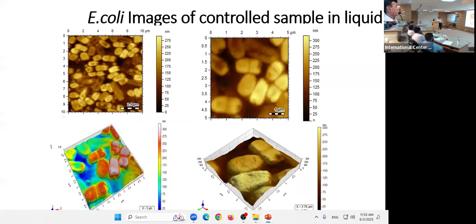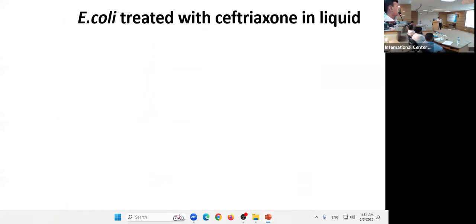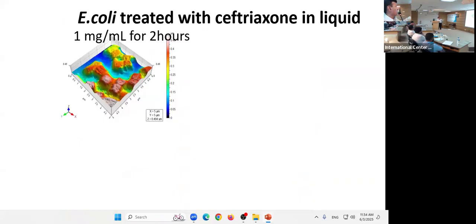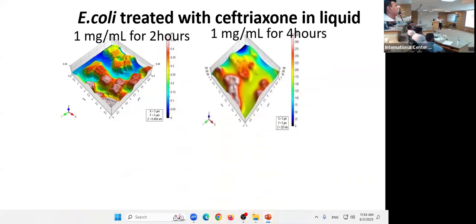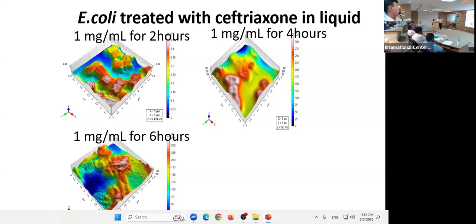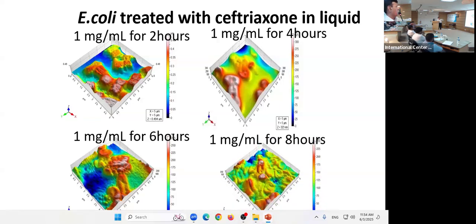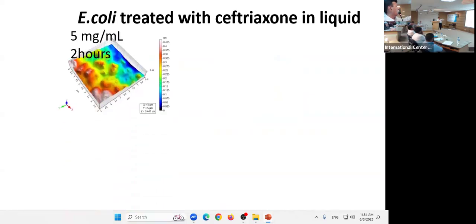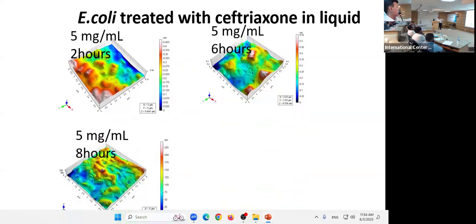Then these are the control samples of the E. coli, and then we treated them with ceftriaxone: 1 milligram for 4 hours, 1 milligram for 8 hours, and so on. This is 5 milligrams of ceftriaxone. You see that when we increase the concentration and time, the bacteria are disappearing. Initially we saw very intact bacteria, and now the bacteria are fragmented.